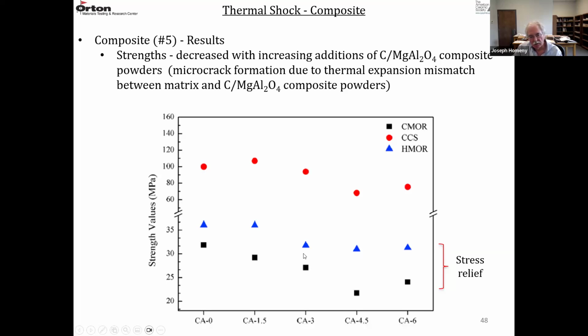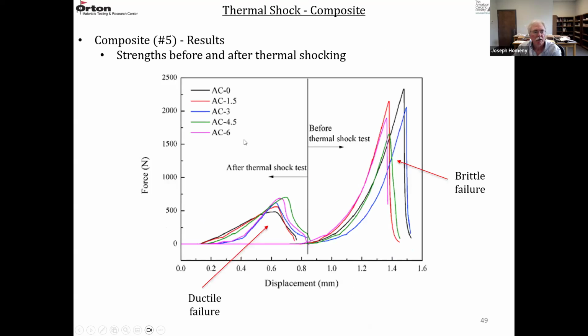And interesting, the hot strength is higher than the cold strength, and they attributed that to stress relief at high temperatures. So the blue triangles are slightly higher in strength than the black squares. So the strength in bending before and after thermal shocking, we have our load displacement curves.